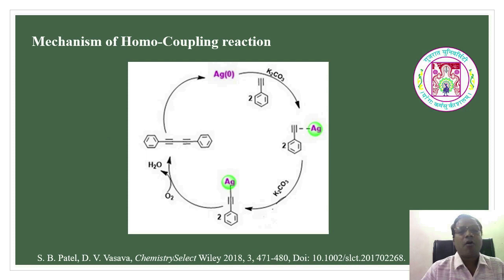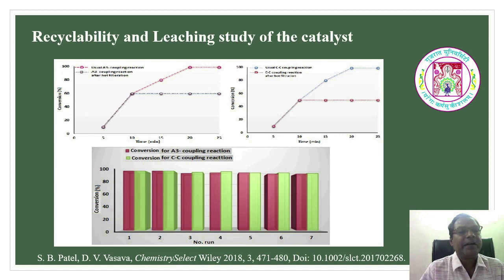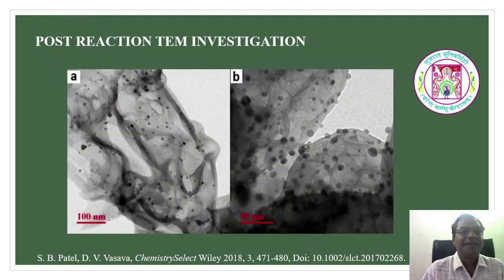This is the possible mechanism of the homocoupling reaction of the terminal alkyne. The recyclability of the catalyst is the key factor of the heterogeneous catalyst. So here the catalyst is recycled after the reaction, and it gives the effective result till the 7th run. After the 7th run, the activity of the catalyst is slightly decreased.